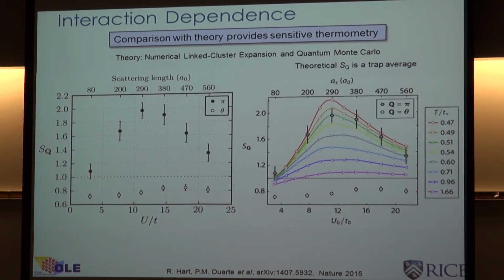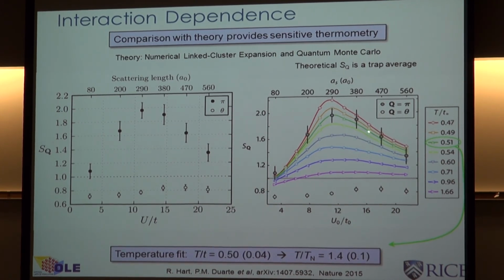Now we can put the theorists to work, and they get out their quantum Monte Carlo and their numerical linked cluster expansion calculations, and they calculate what the scattered signal, what the spin structure function is as a function of temperature and different interactions. And so this is a temperature of 1.6 times the hopping, about 1 times the hopping, 0.7, 0.6. And you can see the signal very rapidly is rising. And our data, if you fit it to this theory, it fits best to this green line. Fits very well to the green line for all the interactions.